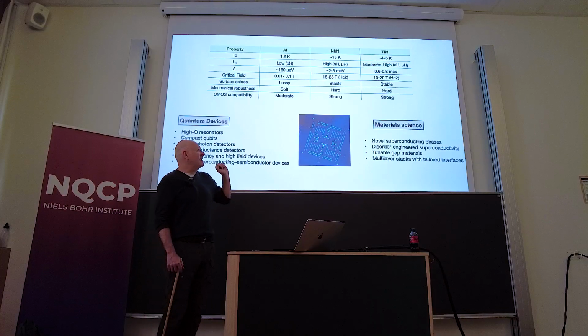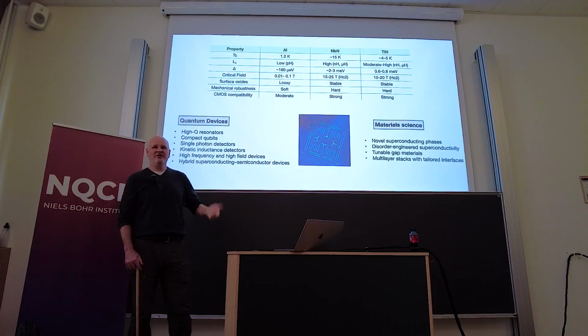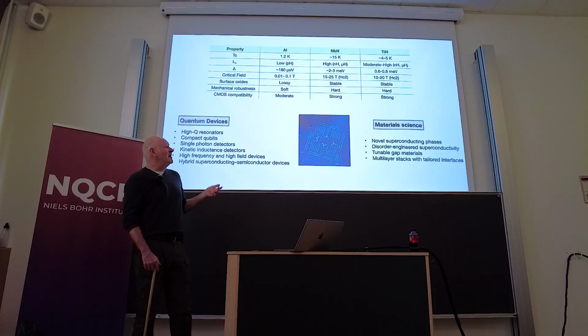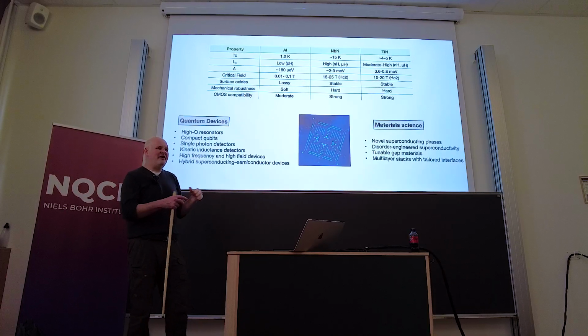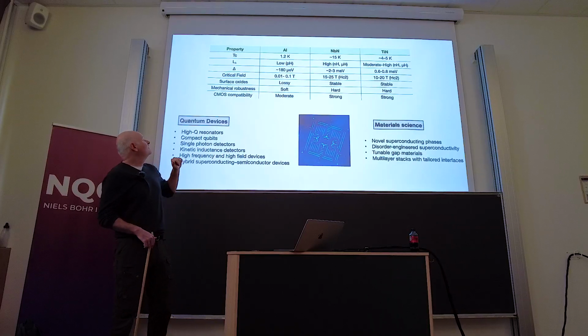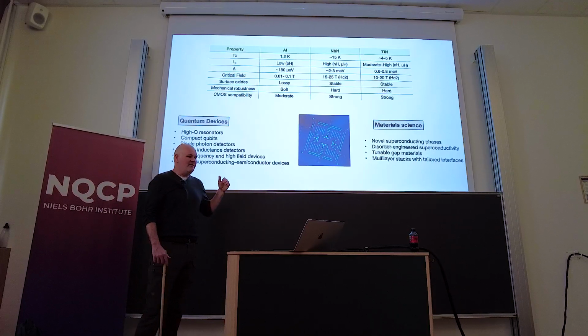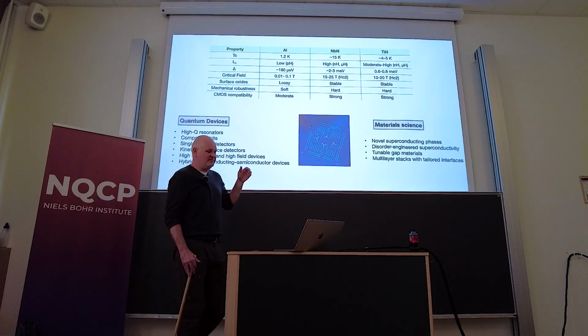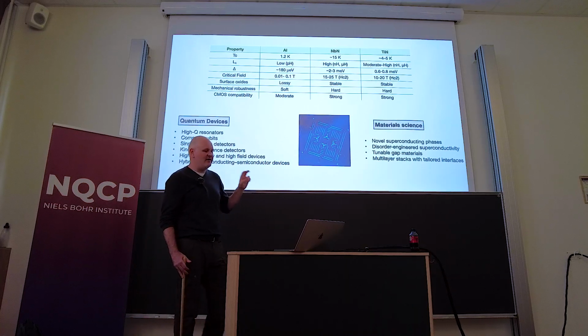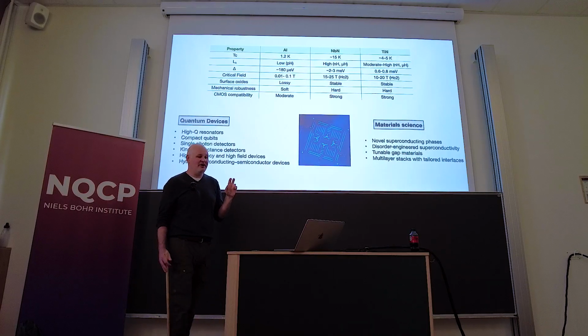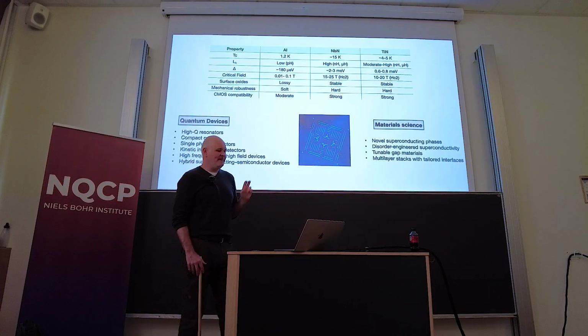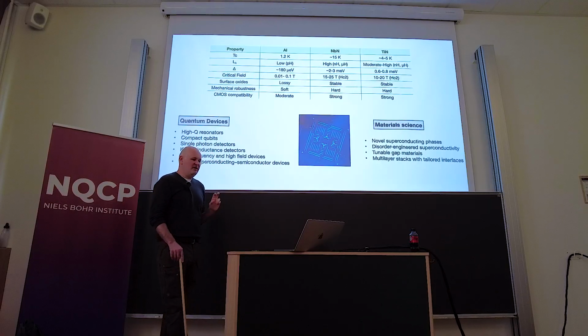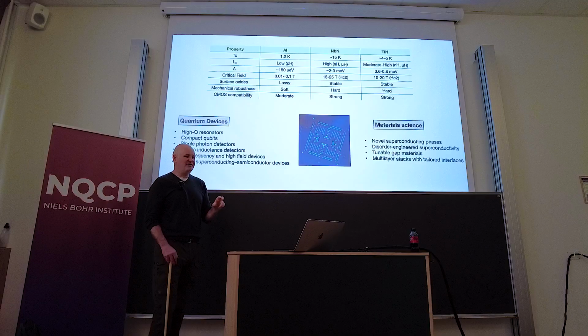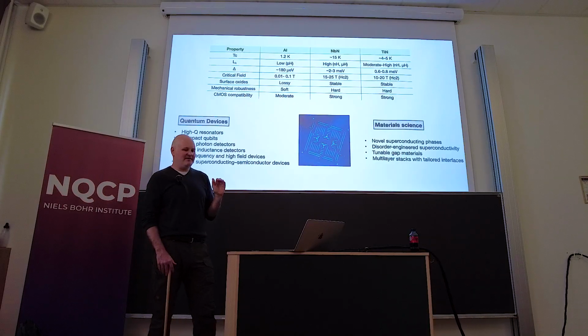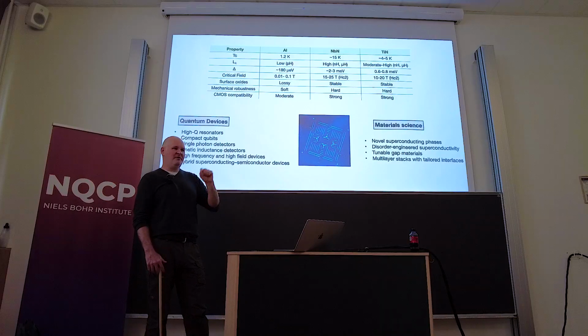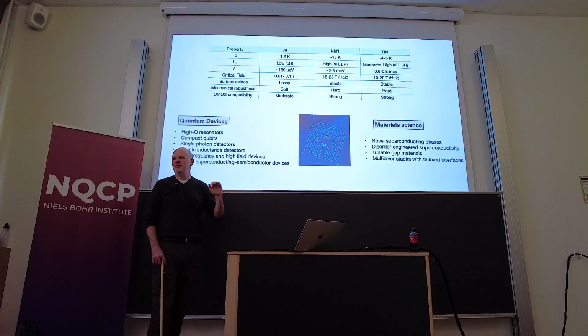But essentially, the nitrides are harder materials. They have more stable oxides. They have less oxide. They also have very, very different properties from the metals. So their TCs are much higher. Their superconducting binding energy is higher. They also have higher critical fields, so they're good for different applications in many cases. But they can also be quite good for qubits. But the problem is that for Josephson junctions, everything right now is completely dependent on the aluminum oxide process. It's very well understood. Everyone uses it.